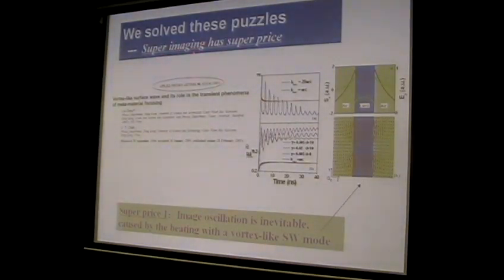In short, we found that this super lens or super image actually has super prices. The first price to pay is that the image oscillation is actually inevitable. It is caused by the beating effect between the working frequency signal and a very special vortex-like surface wave mode, which is there for all electromagnetic systems. For this vortex-like surface wave, the energy flows like this and then goes in the opposite direction inside the slab. So this mode does not transport energy at all.